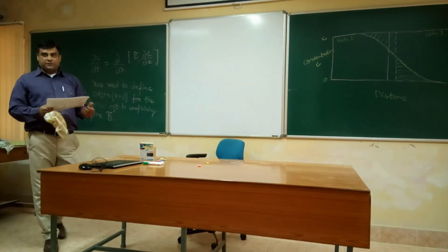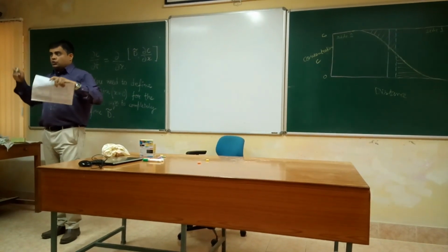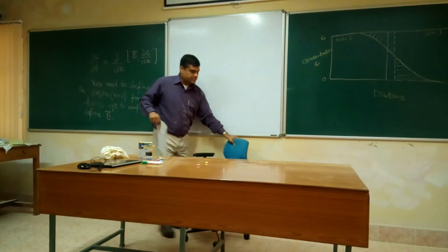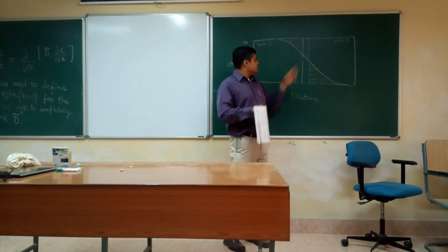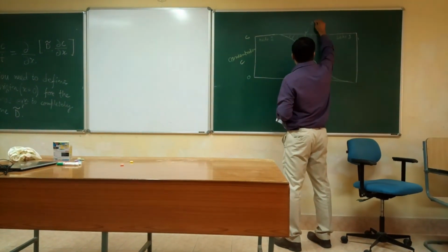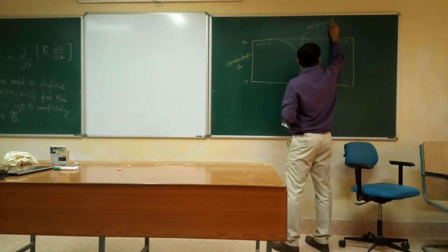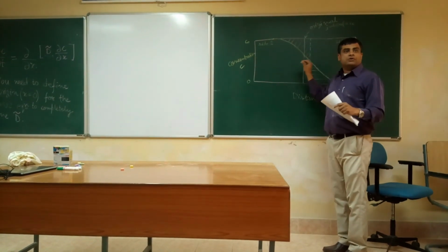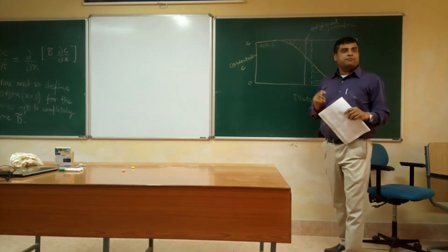For the chemical diffusion coefficient, what is usually done is you butt weld two metals or two alloys like this, whatever I have shown here. So this is your original interface, along this interface. Two sides, two different alloys or two different metals, you butt weld and anneal for a specified time,